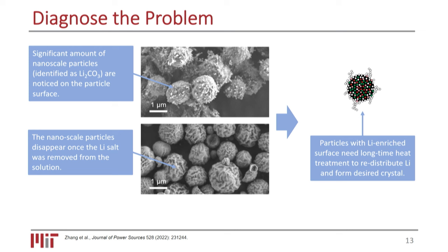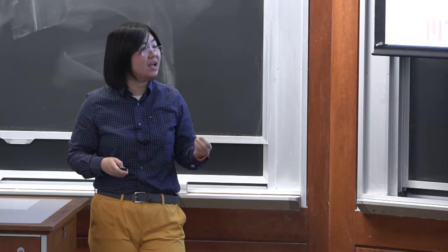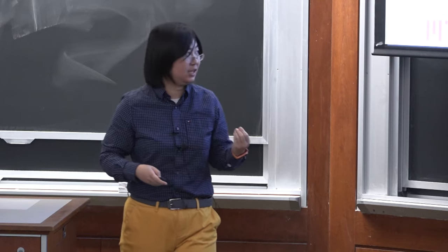And if we do it at a shorter time, we couldn't achieve it. This is because we do see some small nanoparticles, later identified as some lithium salt, formed at the surface of the particle. So if that is the case, then essentially we need a relatively high temperature and long calcination time to have that lithium source diffuse into the particles. And that is the reason why we need a long calcination time.